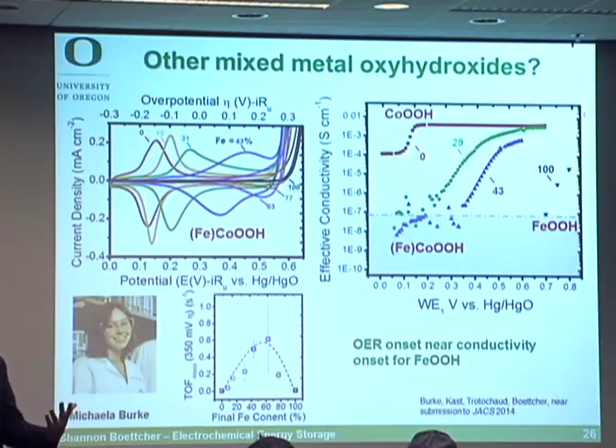Not surprising. But what's interesting is that it does become moderately conductive if you polarize it very anodically. You're probably starting to form some iron 4+, and there's maybe some sort of hopping mechanism. So if you push it hard enough, you pull enough electron density out of it, you apply a sufficiently anodic potential, it starts being a little bit conductive. And what's interesting is this onset of conductivity matches well to the onset of OER activity in the bare iron phase. So why that's interesting is it looks like that iron oxyhydroxide is not nearly as bad of a catalyst as people thought. It's a bad electronic conductor. And the electronic conductivity is essentially gating what you measure as the OER activity.